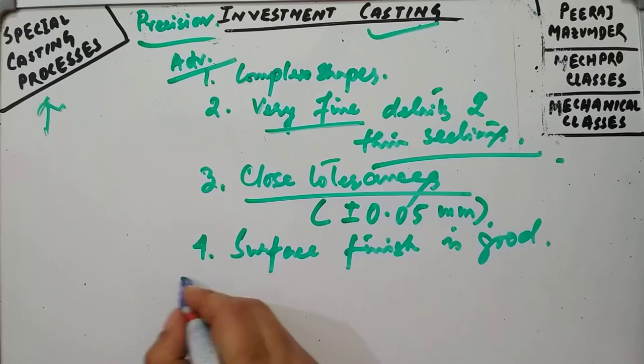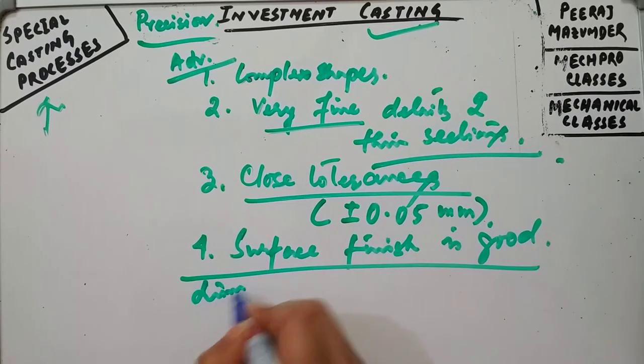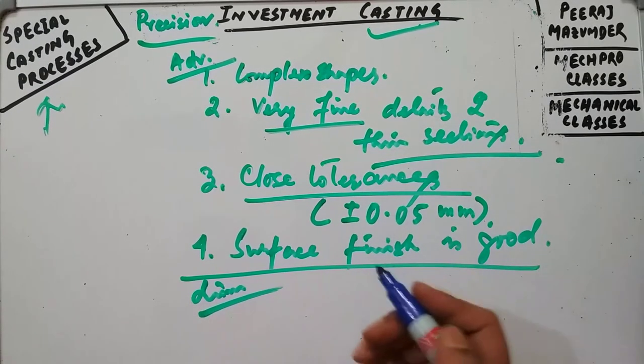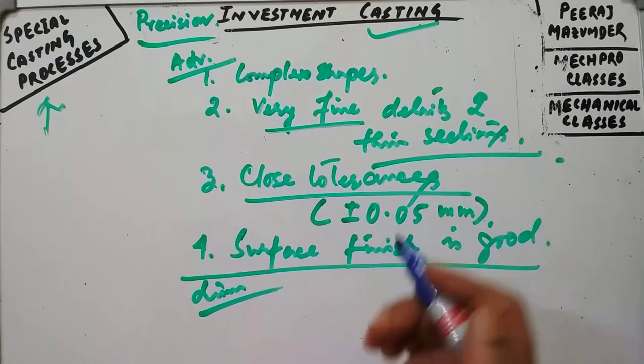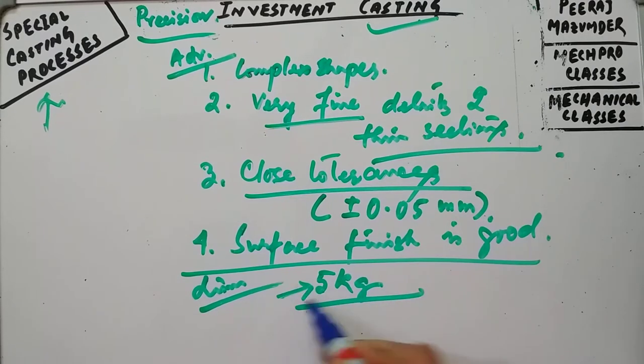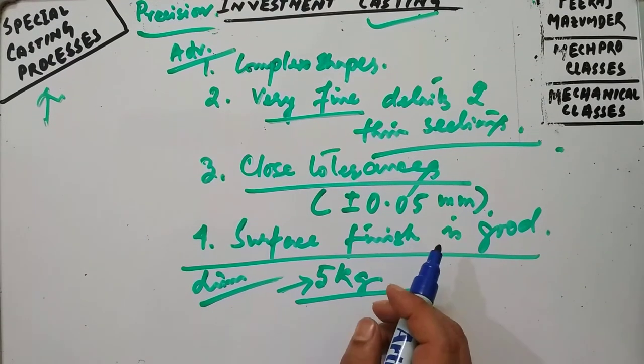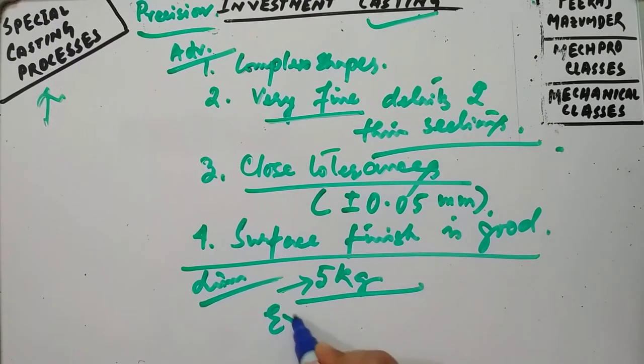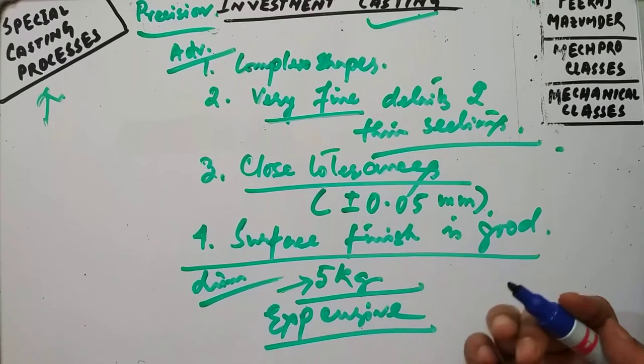With proper care it is also possible to control grain size, grain orientation, and directional solidification. Limitations: the process is normally limited by the size and mass of the casting — the upper limit is around 5 kg. It is also a more expensive process due to the larger amount of manual labor required in preparation of the pattern and mold.